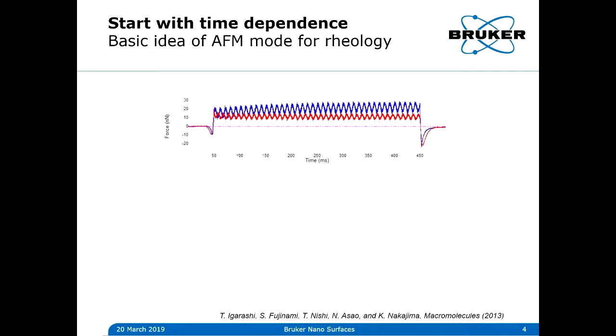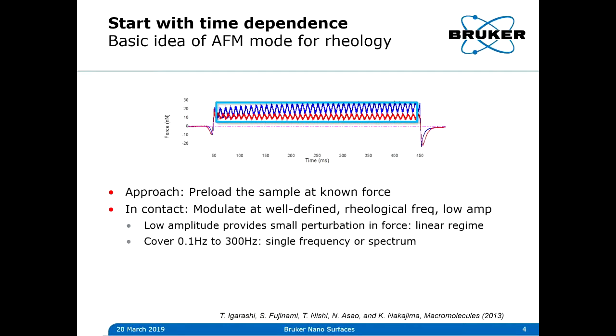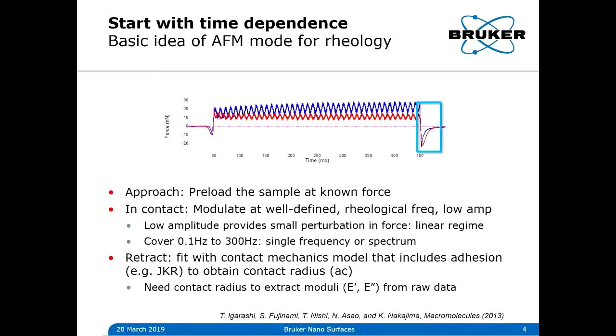So in order to address these, we talked to our collaborators again, and we realized that we needed a different approach, one that provided well-defined rheological frequencies as a perturbation of a carefully controlled preload. So we come into the surface, we preload the sample at a known force. Then, once we're in contact, we modulate at a well-defined frequency, which would also be low amplitude, so we can be in the linear regime. We can control whatever frequency we like, so we can do a spectra if we want to. And then we retract, and we can fit that retract with a contact mechanics model that includes adhesion, for example, JKR, to obtain a contact radius, and that allows us to get our storage and loss modulus from the raw data.